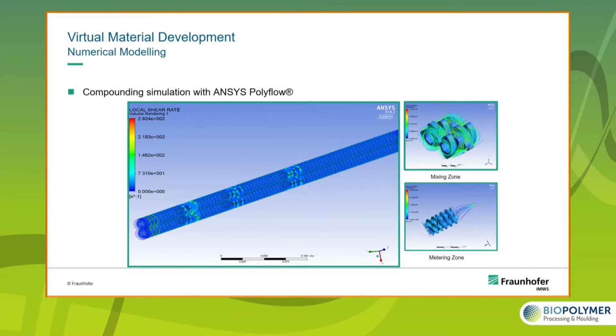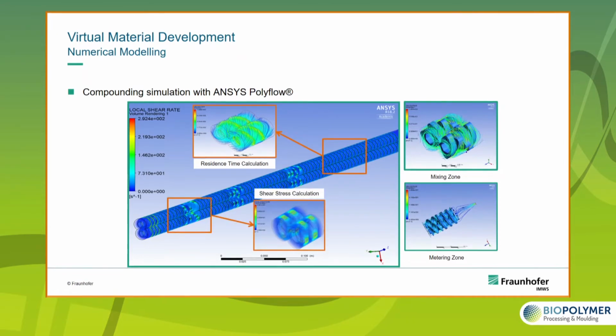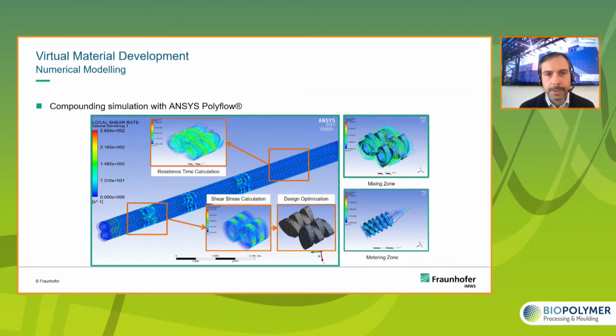So this is a software where you can calculate the residence time, for example, as shown here, of a twin screw compounding machine. You can also simulate the shear stress over the screw. And especially in the mixing sections, this is very interesting because there you have the development of the microstructure of your compound. And this is very important to optimize properties at the end. And of course, if you find out that the screw design you are actually working with virtually is not optimum, you can do virtual design optimizations. And this helps you to find the optimum design and process properties.